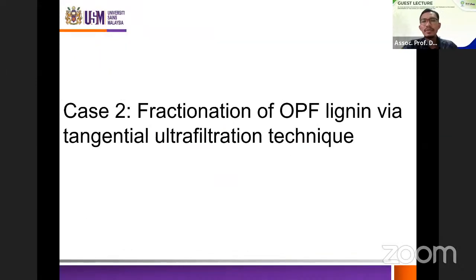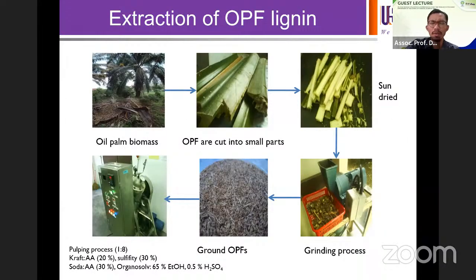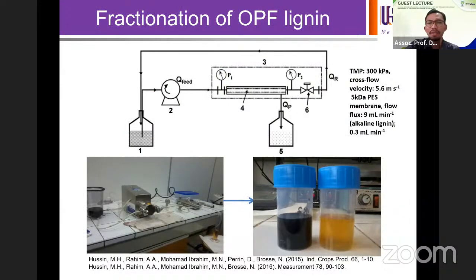And another technique that we use is fractionation using ultrafiltration. But first, we need to obtain the black liquor from a pulping process. So this is almost similar to what I explained earlier on. After we have obtained the black liquor, we subject it to the ultrafiltration membrane. The membrane functions like a filter. It separates molecules with a specific molecular size, which in this case, we are using a membrane at around 5,000 Dalton, or a 5 kDa PES membrane.